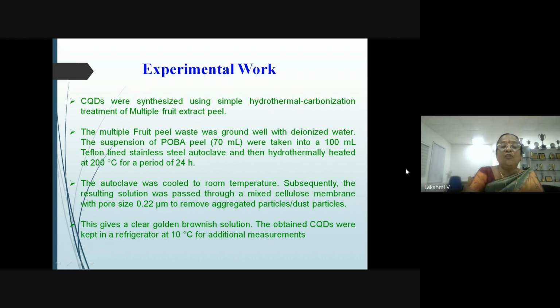The suspension of this POBA peel, 70 ml, was taken into a 100 ml Teflon-lined stainless steel autoclave and then hydrothermally heated at 200 degrees Celsius for a period of 24 hours. This can be done in the laboratory itself, sir. And we were trying with first 1 fruit and then 2, and now we have gone to 4 fruit peels. The autoclave was cooled at room temperature.